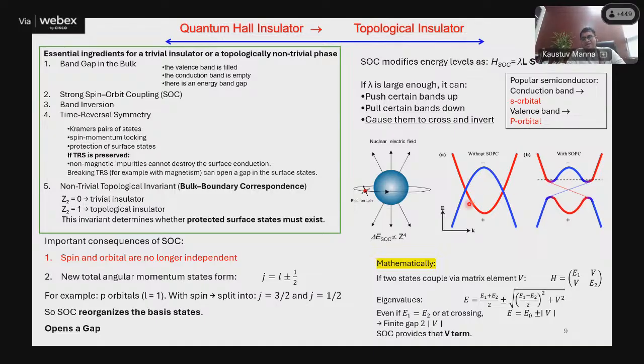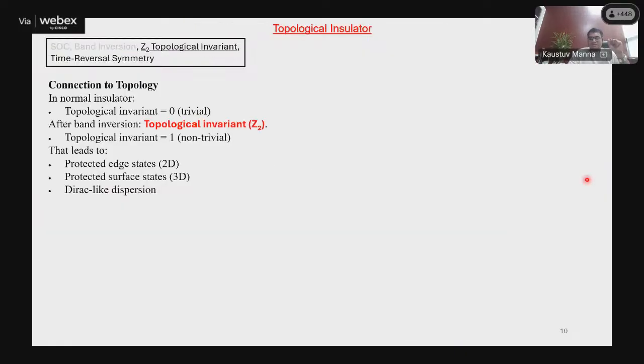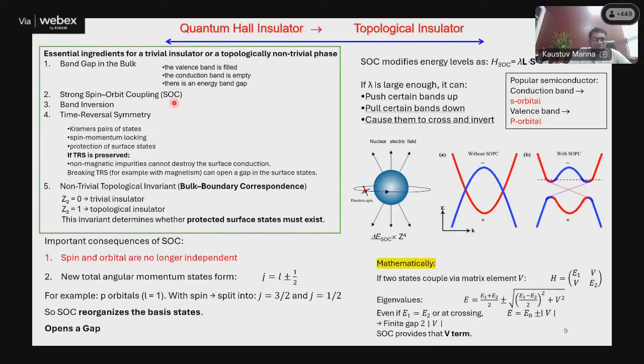That means after the band inversion, once you incorporate SOC, once you have the hybridization, the bulk automatically gaps out. So in the bulk, you satisfy the condition that the bulk must be gapped. With the SOC, with the band inversion, now you have achieved the state that the bulk is gapped out. Okay. What is the next consequence? As you can see, because of the band inversion, part of the conduction band has gone to the valence band, whereas part of the valence band has gone into the conduction band. As a consequence, you give rise to Z2 invariance. What is Z2? By the way, I'm going step by step.